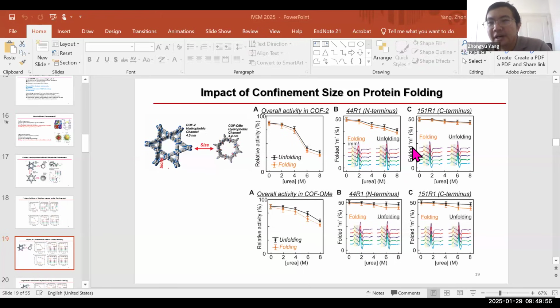Then to trigger the folding, I wash the MOF loaded with 8 molar urea unfolded protein with, say, 4 molar urea. I wash a few times. I let it equilibrate for 30 minutes to 1 hour, and I wash again, making sure everything is at 4 molar urea, and then I run EPR again. So it is a thermodynamically equilibrated state, which we can run EPR on for a few minutes.